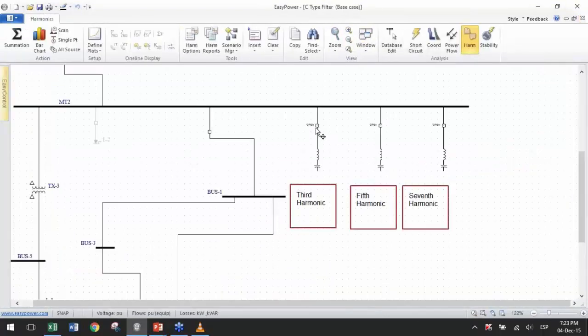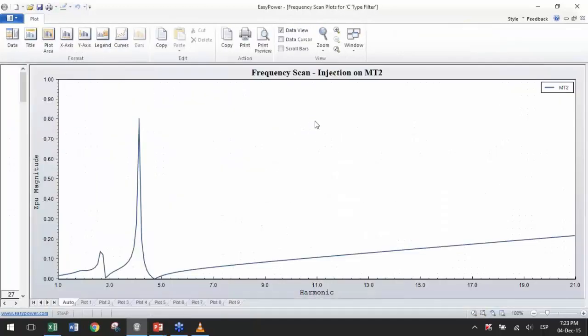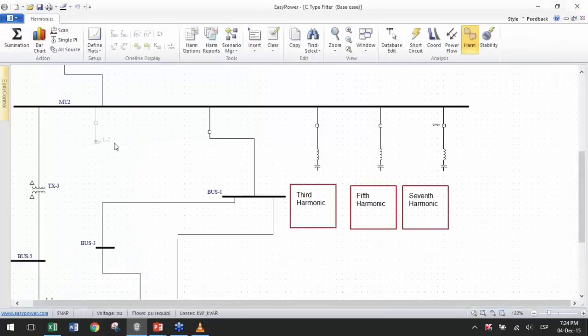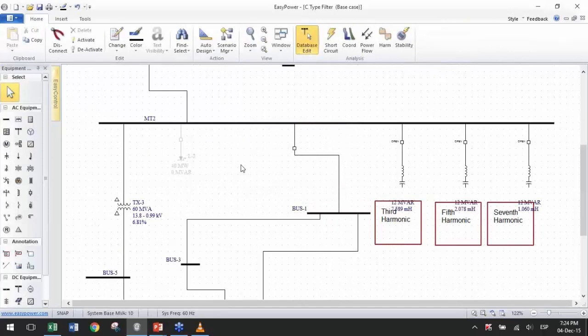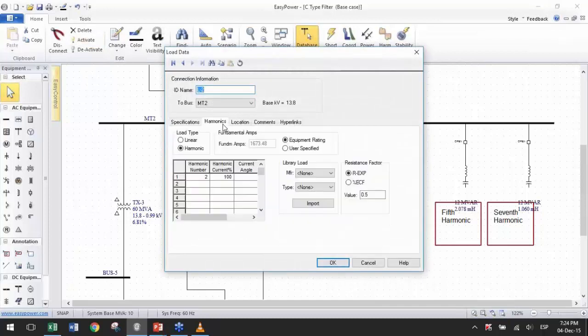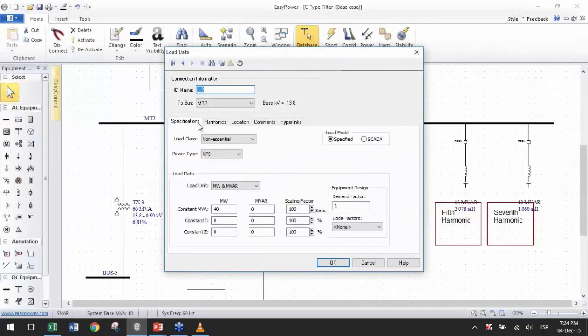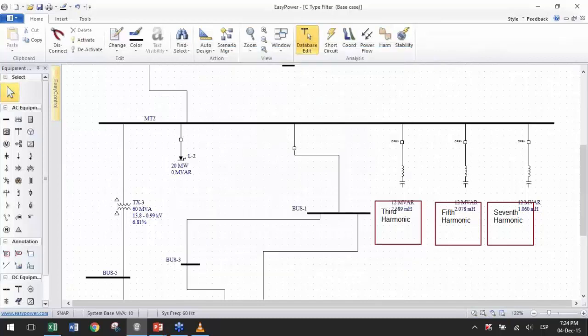Now, what happens when I add the other filters? Let's say the third and the fifth harmonic. I have the resonance from the fifth harmonic filter, the resonance from the third, but on the second harmonic, which is the one I really care about in the arc furnace facility, I have no resonance. Therefore, I will not have second voltage harmonic distortion. And to make an example out of this, I'm going to make a truly worst case scenario where I place a lot of harmonic current just from the second harmonic, maybe a 40 megawatt system, let's say 20. So in all, it's a lot of harmonic current.